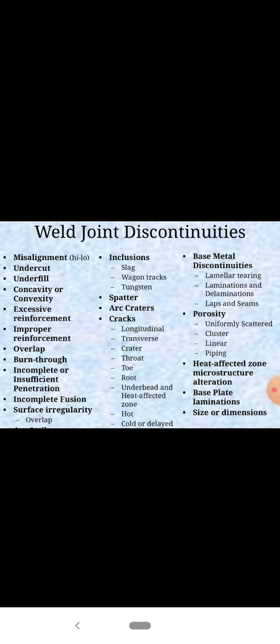And a defect may also be called an interaction of the weld metal with a defect in the base material, like some kind of impurities, and higher temperature material existing in the base material, and that base material carrying these discontinuities or defects hidden inside them, and due to that these kinds of defects arise. So the undesirable metallurgical structure, which we do not require, is gained due to the grain size and the hardness of the particular weld specimen as well.